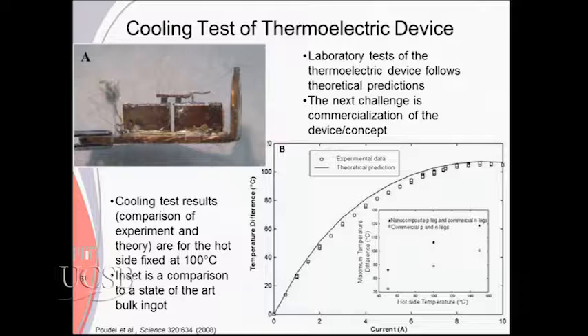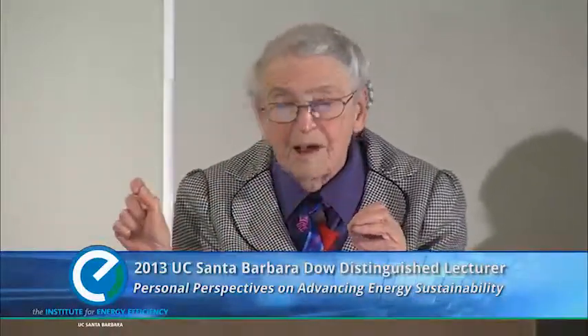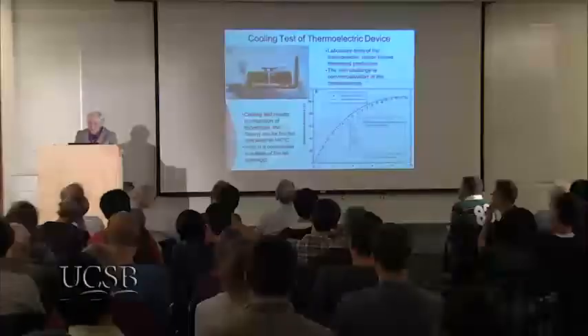When you read the literature, you're never quite sure that the people have done the experiment correctly. And the problem is that the theory is for all the parameters, electric current, thermal conductivity, Seebeck, everything: you have to measure in the same way. You set up a coordinate system and you have to go with the same coordinates. And maybe half of the papers or a large fraction of the papers that you read in the literature don't make a careful effort at doing this, and they assume that these properties are isotropic, but they may or may not be isotropic. So you have to really read between the lines and see that the people have done the experiment correctly.